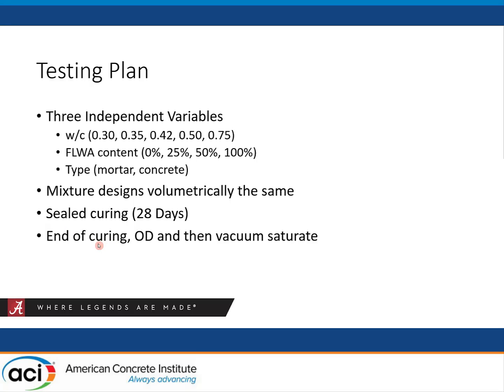And then at the end of that 28 days of sealed curing, we'll go ahead and oven dry it. We'll actually take a resistivity measurement of the oven dry sample. Our impedance analyzers can actually measure this, although it's not really that useful. It's just a neat thing to do. But most importantly, after we oven dry, we'll vacuum saturate it and then take a final resistivity reading.